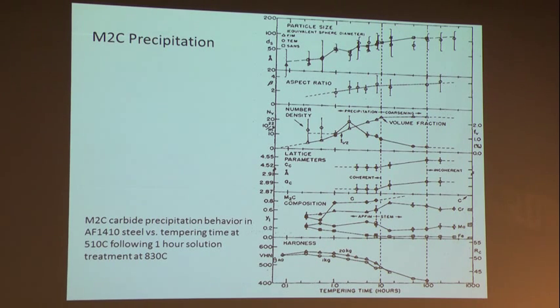And what this thorough characterization allowed us to do is to validate the theory of precipitation at high supersaturations, which allowed us to parameterize that precipitation behavior, in which thermodynamic driving forces control particle size, and diffusion rate constants determine the time scale. And then this enabled a parametric approach to the design of a precipitation strengthening efficiency in these steels. With those methods, we've been able to design steels that for a given carbon content are 50% stronger than the previous steels.